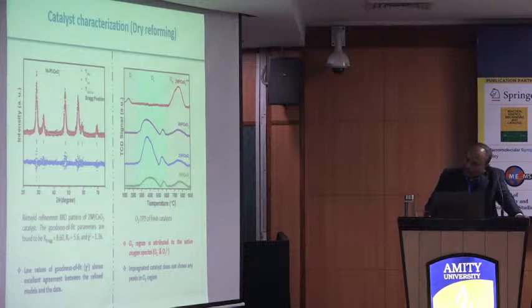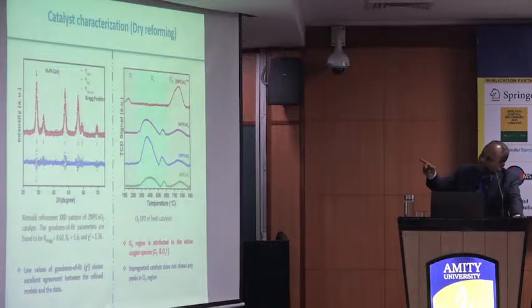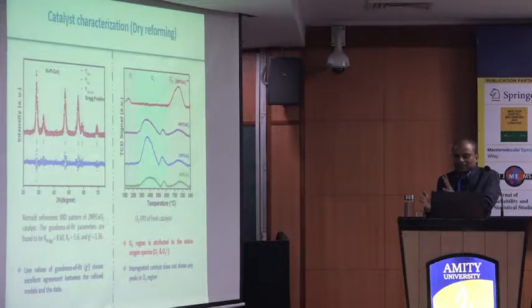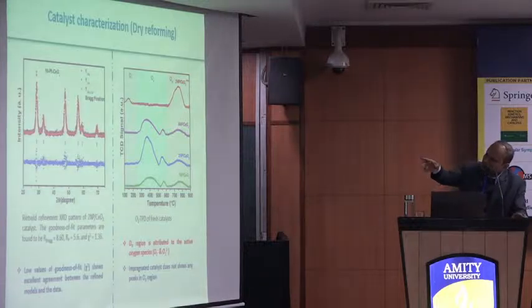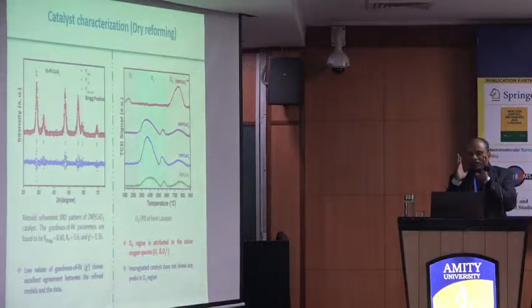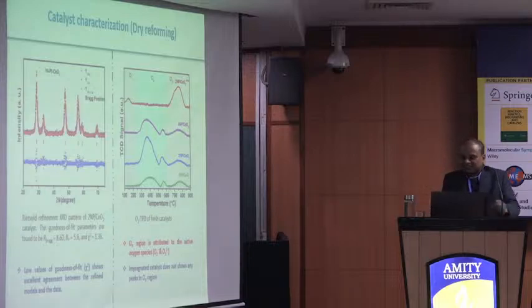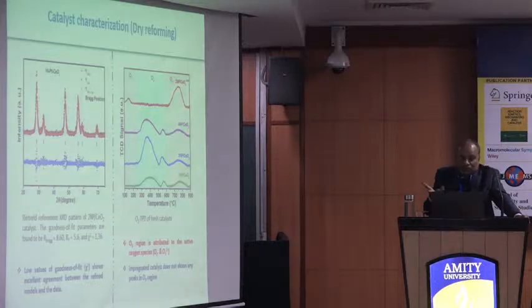This is the XRD. We have done Rietveld refinement analysis and found that platinum and nickel have gone inside the ceria lattice. And also we have done oxygen TPD here. You can see here that the second region means there is some weakly adsorbed oxygen species here, and that is the most active species for this reaction. And we call this superoxide species.